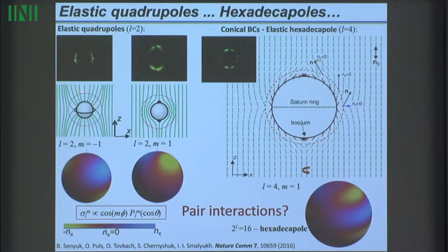Because as you would look at the tilting of the director around these particles, and for example, if you were to plot on some surface surrounding this particle the x component, perpendicular to the far-field director, of the director field, you would have this kind of negative and positive signs of this x component alternating around these quadrupolar colloidal particles in a very similar way to what you would have in the case of quadrupolar charge distributions on spheres in electrostatics, where you would describe these distributions with this expression in here.